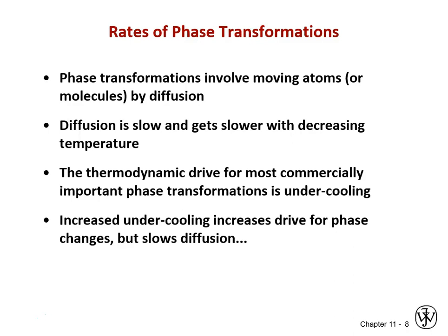So we lower the temperature in order to drive our transformation, and we saw that undercooling drove it hard in at least 3 respects: rate of nucleation, nucleus radius that was stable and would continue to grow, and then the energetic barrier to grow. But yet, if you can't move atoms to rearrange in phases, it's not going to grow regardless of the drive.